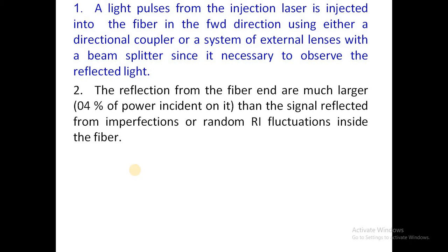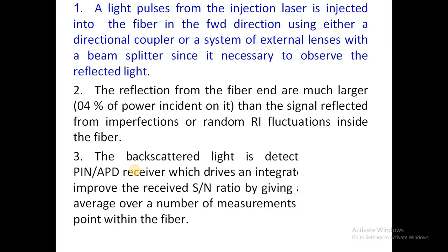The reflection from the fiber end is much larger, 4% of the power incident on it, than the signal reflected from the imperfection or random RI fluctuation inside the fiber. So how much reflection can occur, that we have to find out.